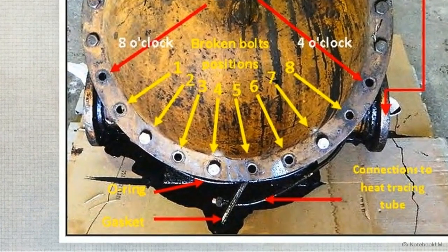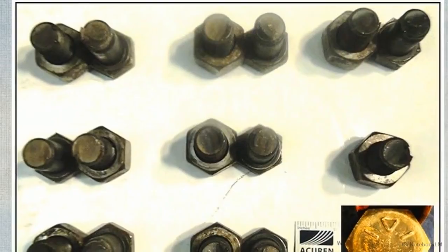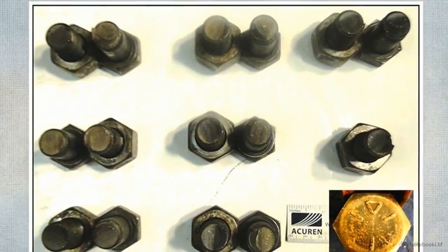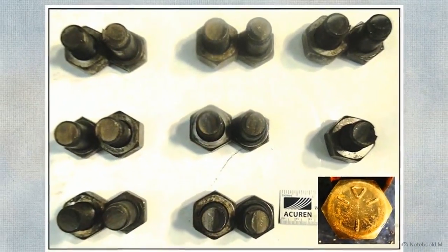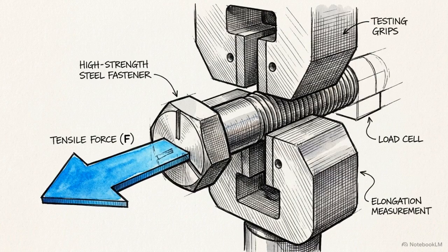Consequently, the internal seal was destroyed, with the rubber O-ring and gasket extruding from the joint. These are the actual severed fasteners recovered from the site. They are 3/4-inch, grade 5 high-strength steel bolts. Hardware of this caliber possesses a tensile strength designed to handle loads vastly exceeding a 60 psi operating pressure.